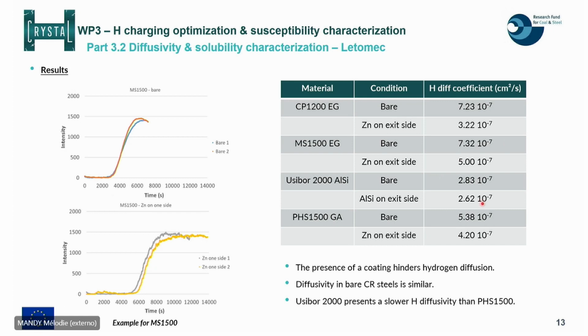You see that what we could expect also is the fact that the presence of the coating generally hinders hydrogen diffusion, so diffusion coefficients are smaller. Diffusivity in bare cold-rolled steel is quite similar in both of them. And for the PHS steels, we see that Usibor 2000 apparently shows a slightly slower hydrogen diffusivity than PHS 1500.